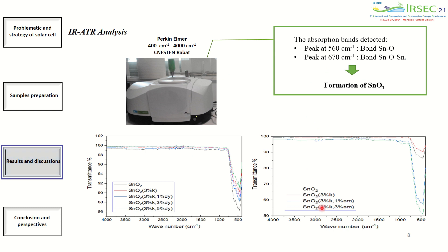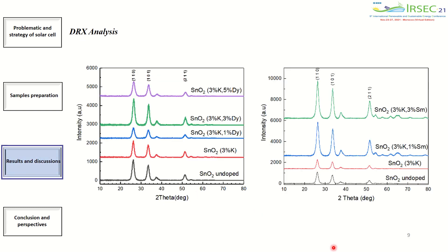The first technique is Fourier Transform Infrared Spectroscopy, which is a method of structural analysis. The resulting IR spectrum shows two broad bands at 560 and 670 cm⁻¹, associated with the vibration and extension of Sn–O and Sn–O–Sn bonds.